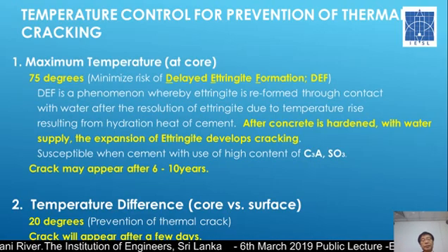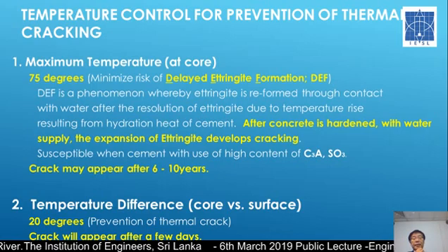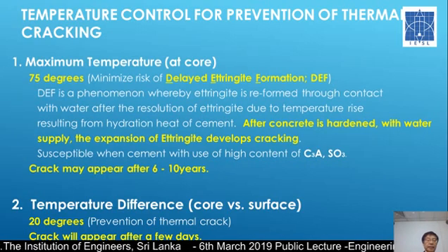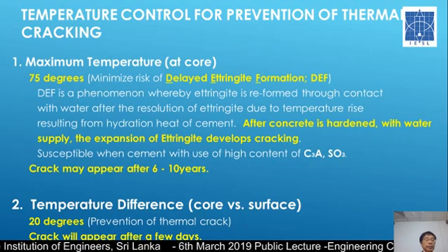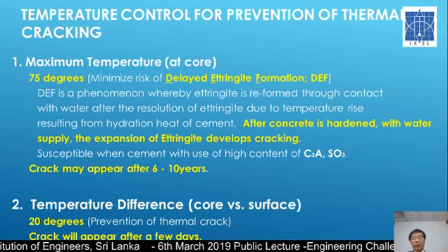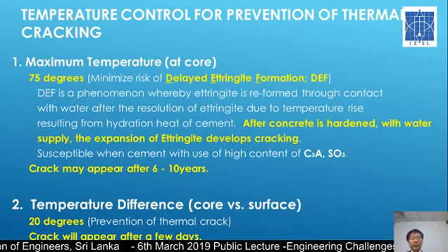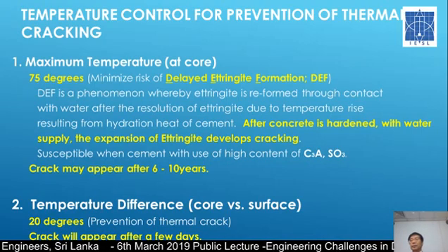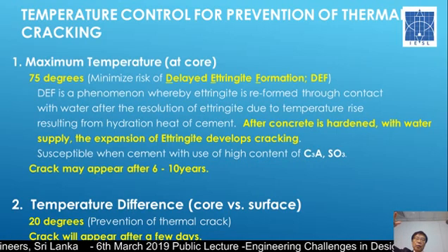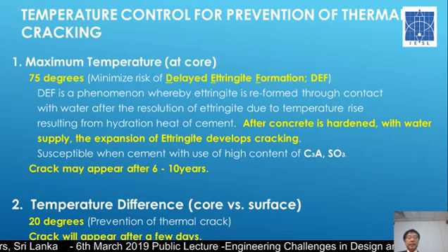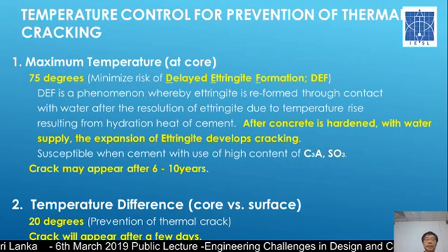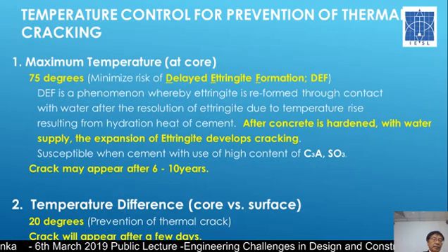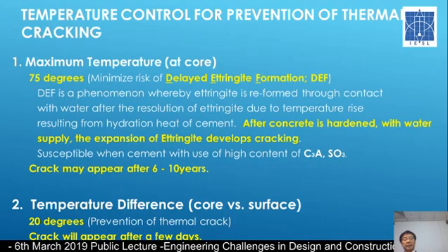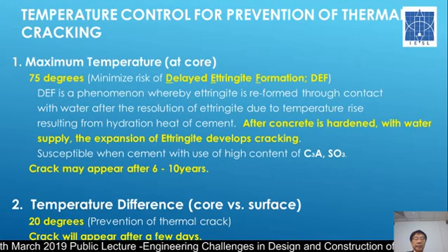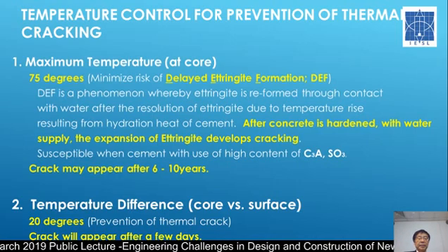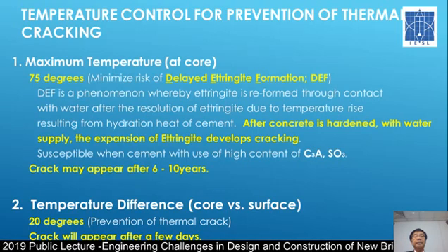Now, why do we need to control the temperature? It is to prevent thermal cracking. One is that we have to control the maximum temperature which occurs at the core of the structure. And another one is the temperature difference between the surface and the core, which creates cracking. Now for the maximum temperature, it is said that it should be less than about 75 degrees. And this is to prevent delayed ettringite formation, DEF.